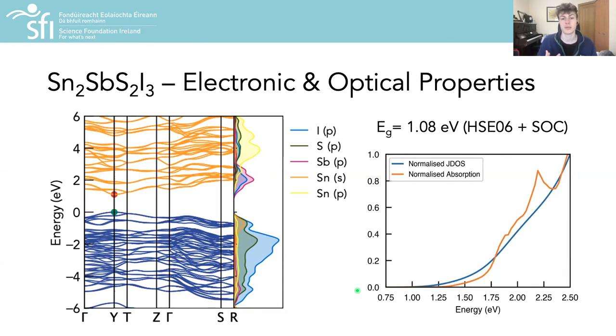From close analysis of the electronic wave functions, we identified the symmetries and spatial separation of VBM and CBM states as the origin of this weak but non-zero transition dipole moment just above the band gap.